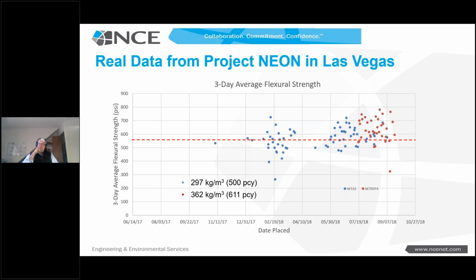That's a lab study. This is a project that I worked on in Las Vegas, Nevada. It's called Project Neon. It was about a $750 million I-15 reconstruction job right through downtown Las Vegas. This is real data collected on that project, where we looked at a 500 pound per cubic yard mix in contrast to the DOT's mix, which has a minimum cementitious content of 611 pounds per cubic yard. What you see in this data is effectively almost no difference between the higher and lower cementitious content, a little bit at 3 days, but look at the time frame when this was done.